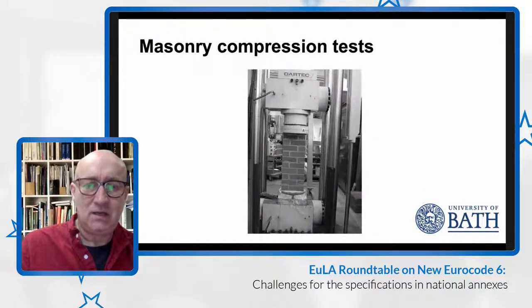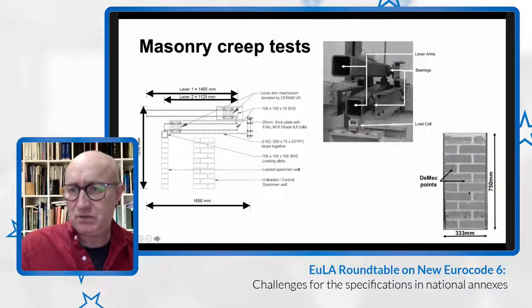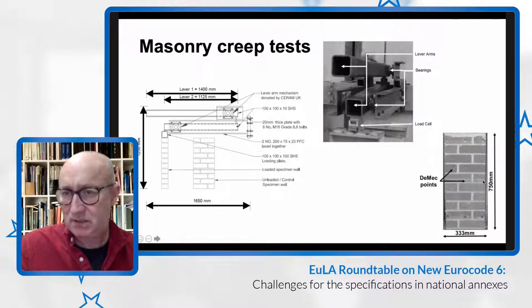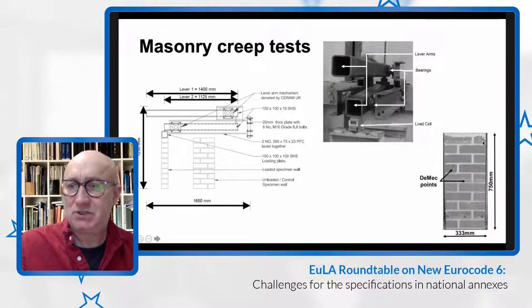And then for the wall tests, we used DeMec strain gauges, and you can see pairs of the gauges here. For those of you not familiar with the DeMec strain gauge, essentially we're measuring vertical strain here. So we're measuring change in height. We did also attempt to measure some lateral strain, but they weren't very successful. So we primarily reported on vertical strain. We're measuring in a pair across from there to there and from there to there.